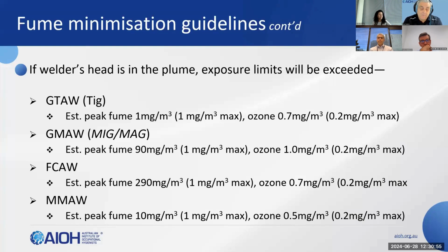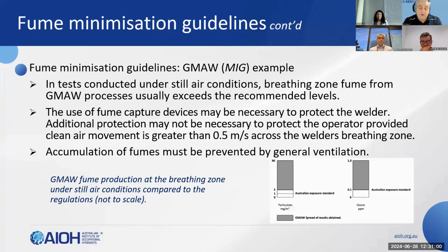The next slide, please. Now, by way of example, shown here is the result summary for gas metal arc, or the MIG-MAG process as it's known in Europe. Included are recommendations on the minimum required fume control methods. For this process, the use of fume capture devices may be necessary to protect the welder. An additional protection may not be necessary to protect the operator, provided clean air movement is greater than 0.5 meter per second across the welder's breathing zone, and the welder's head is not in the plume. And I stress, not in the plume.